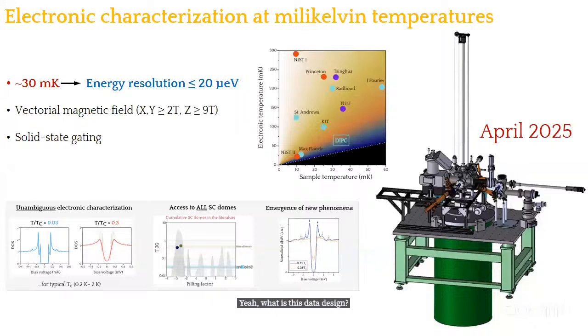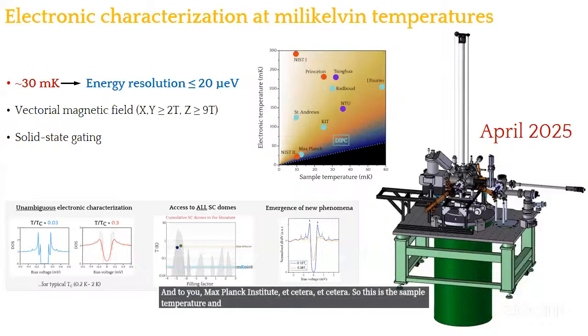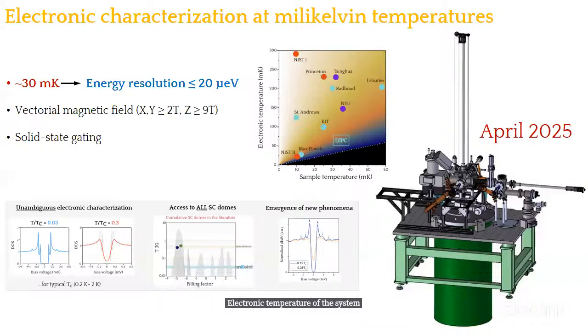The dotted line. Okay, so what I'm plotting here is the sample temperature. Each dot represents an STM system, placed in, I don't know, NTU, Max Planck Institute, etc. So this is the sample temperature, and this is the electronic temperature. The electronic temperature of the system cannot be lower than the sample temperature.